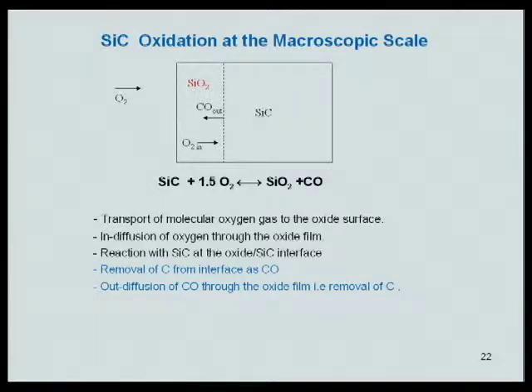But sometimes all of the carbon is not removed. And so the speculation has been for a long time that the reason there's a high density of defects at this interface, compared to the low density of defects in silicon, is because of excess carbon. Now, in the case of silicon, the interface is not perfect, but when the sample is exposed to hydrogen, hydrogen can diffuse in, and hydrogen interacts with whatever defects are at the surface and passivates them. In other words, it saturates any dangling bonds of silicon and renders those defects electrically inactive.